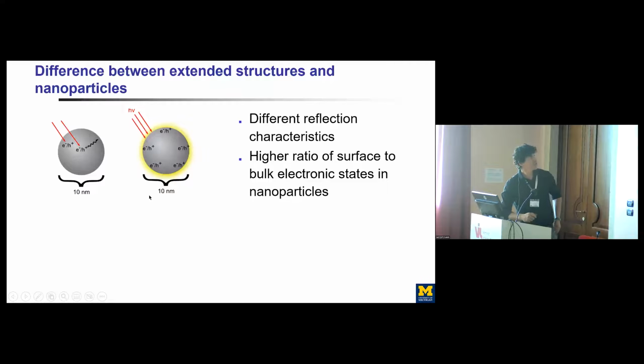So now when we come to the concept of a metal nanoparticle compared to this extended metal surface, there's a couple of differences. First, obviously, reflection is different, but a very important difference is that there's a higher ratio of surface to bulk electronic states. What this means is that if you have a large surface area compared to volume, you're going to push these electronic excitations closer to the surface.